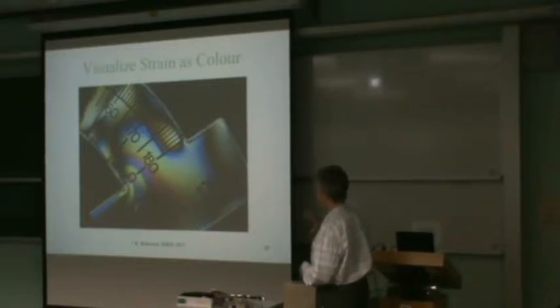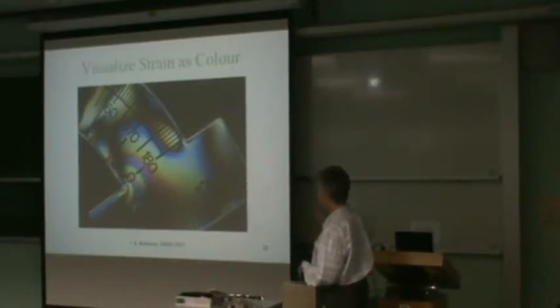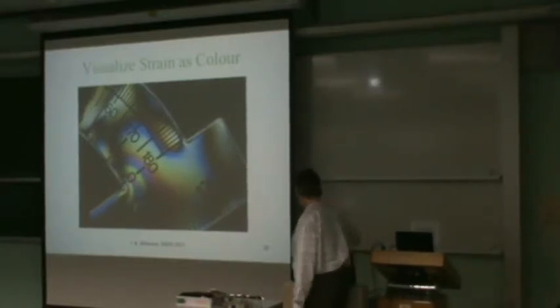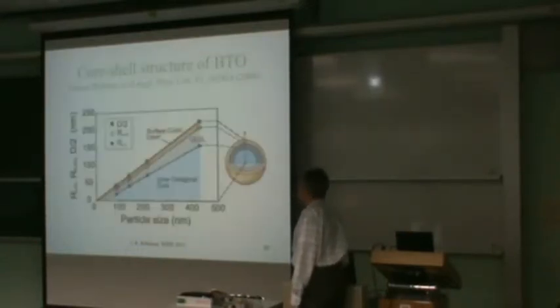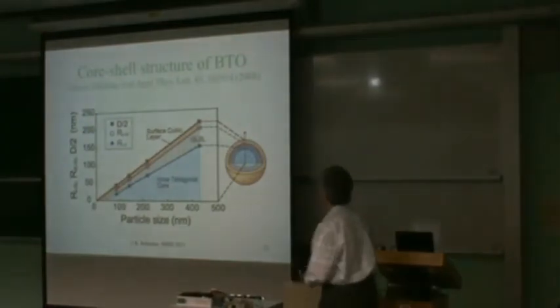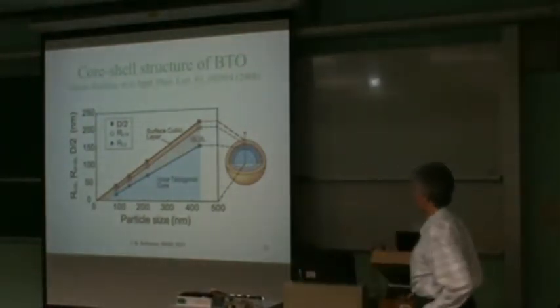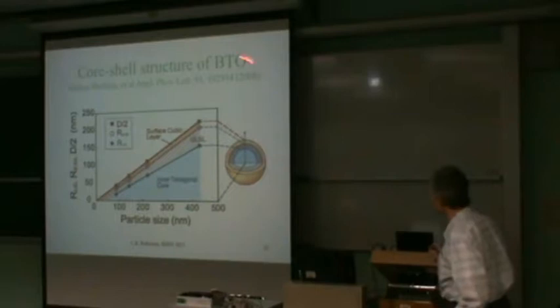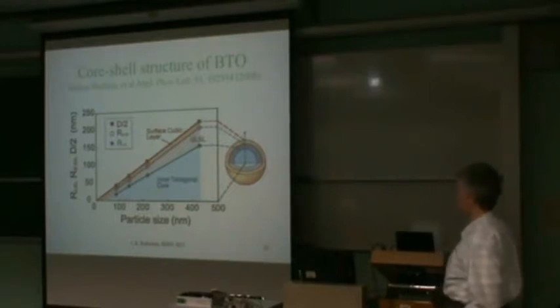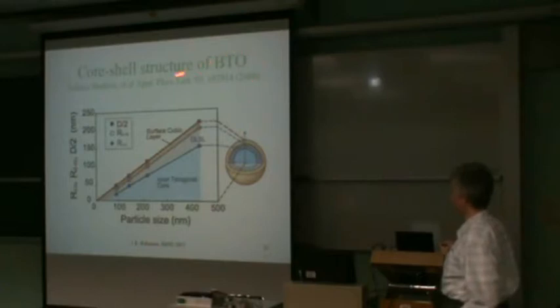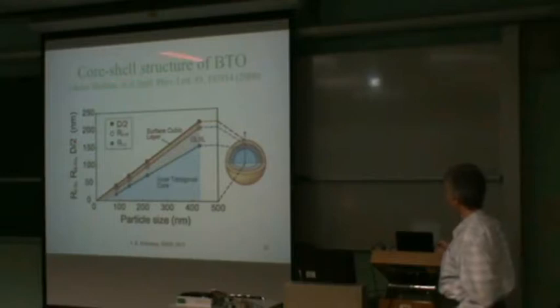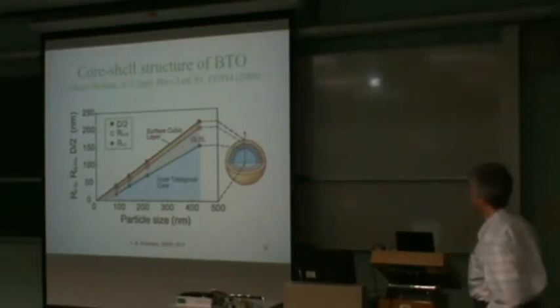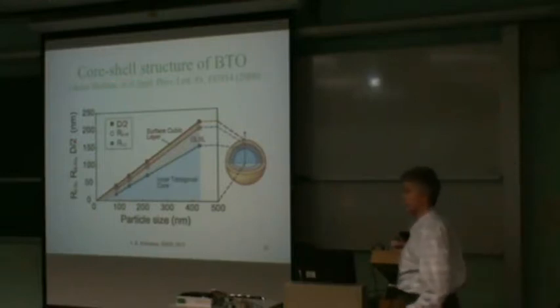And so you can see the slow varying phase that corresponds to the strain distribution inside the material as well. Okay, so here's another example. It's an electronic material, barium titanate. What we're looking at in the experiments I'm about to show are nanocrystals of barium titanate. These are used in supercapacitors.